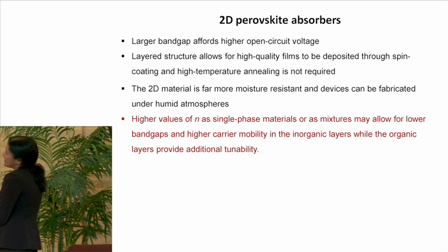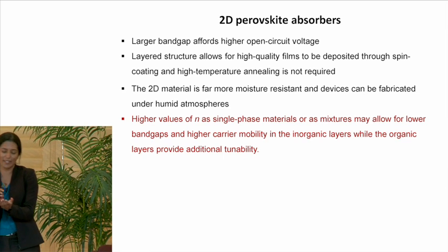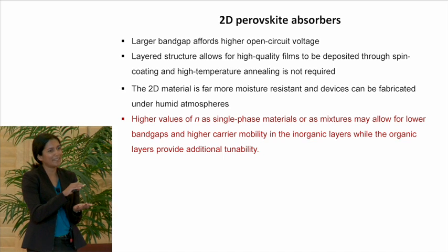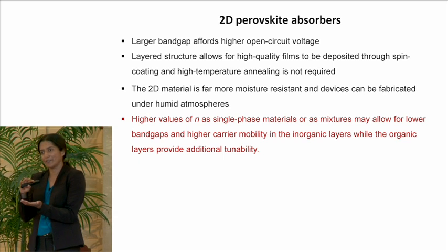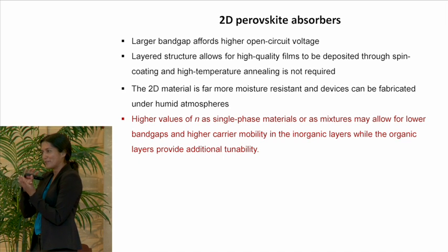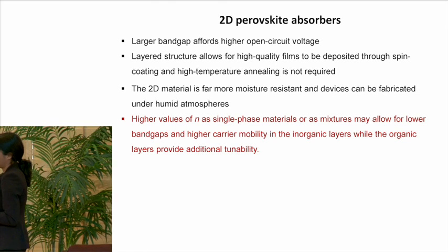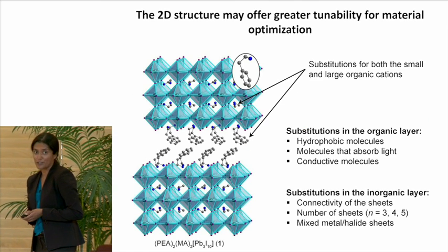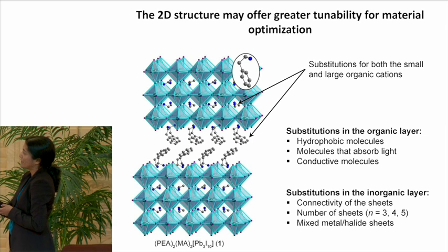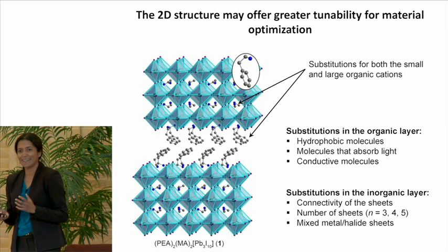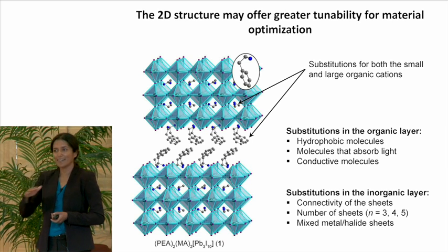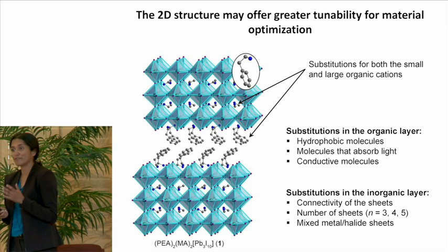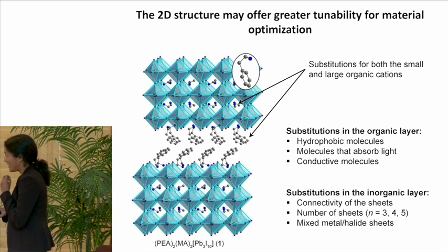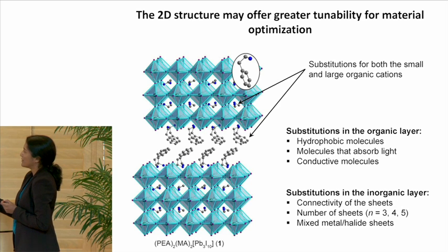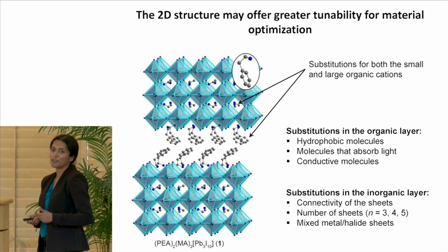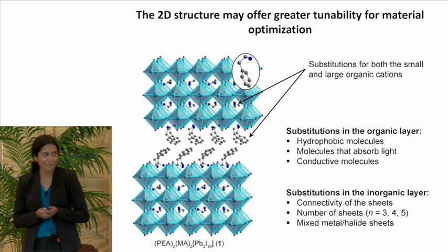So we think that there might be a critical value of N where we can make the inorganic layer just thick enough that it pretends it's a 3D material and has all the beautiful absorption properties of the 3D structure, while the organic functionalities can bring new functions into these materials. So you can imagine putting fluorocarbons here. This would look like you've taken your 3D material, sliced it, and coated those sheets with Teflon to improve the moisture stability at the atomic level. And we can imagine even molecules that absorb light or transport charge to bring new functionality to these materials.